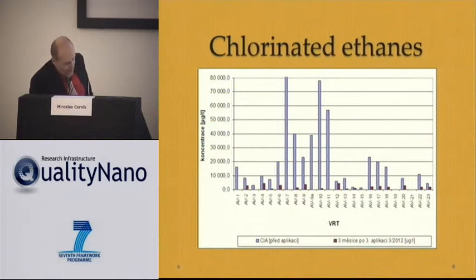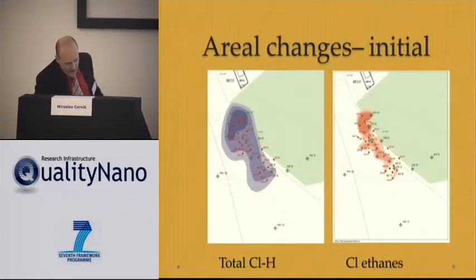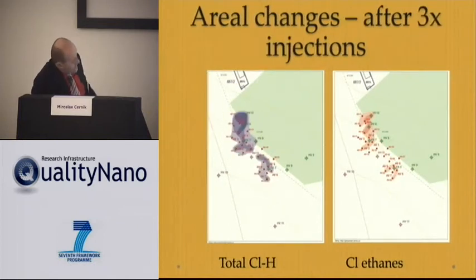The blue ones is before the application, and the red ones, which you almost don't see, is 3 months after the application. So there is really a huge difference in concentration of these contaminants. If you look at the areal changes, this is the initial situation, and this is the situation after the third injection. It's not totally clean because there is a so-called rebound effect, because the contaminants are in pores and in some low permeable parts of the soil, and then it gets back to the water, so it needs more than 1 re-injection to clean it totally.